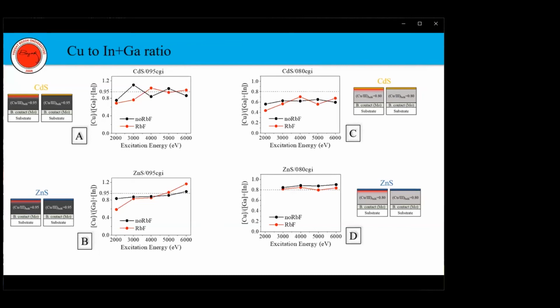Application of PDT induces a copper depleted region towards the surface, which can be seen as a downward curvature of the red colored data in both cases. However, this effect is more pronounced in case of the copper poor sample in figure C, where the copper depletion goes up to the last data point, whereas the effect is limited to the very surface region of the copper-rich sample in figure A. If we compare figures B and D, the relative copper concentration of the untreated copper-rich sample lies around or a little below the bulk value as expected. However, the ratio for the copper poor sample in figure D lies slightly above the bulk value.